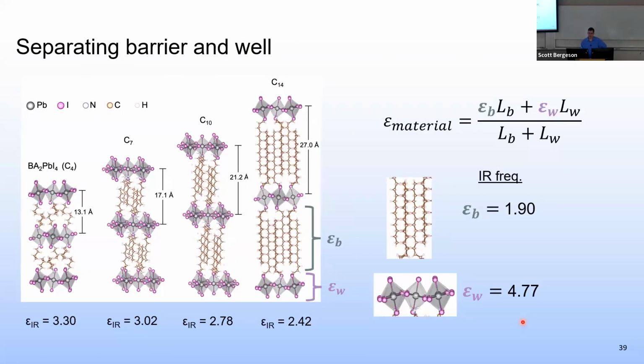Because when you measure a dielectric constant, or even when you calculate a dielectric constant, you're getting the dielectric constant of the whole material. And this model requires separate dielectric constants for the wells and the barriers. But by doing something really clever, this is Cameron's idea, to do a weighted average of the barrier and well dielectric constants, and say this is what the dielectric constant of the overall material is. And then we could figure out, by doing a bunch of measurements, we could do some fitting and figure out what the barrier and the wells would need to be. And it turned out to be pretty self-consistent, and gave us the values we needed for the theory.